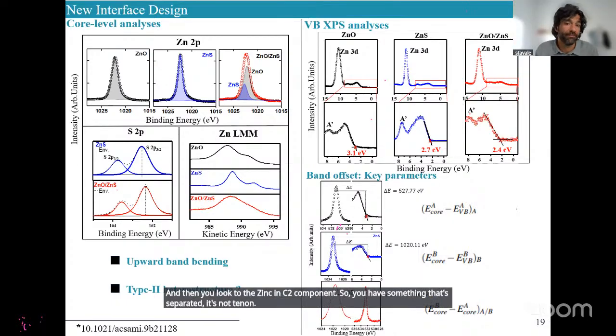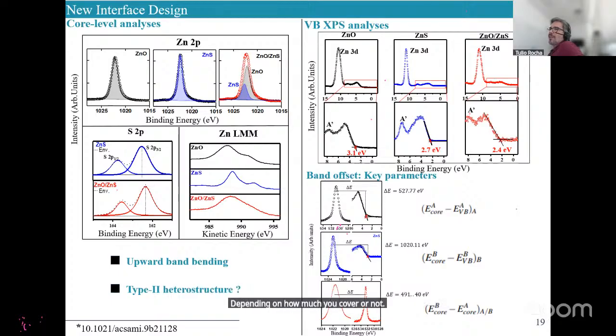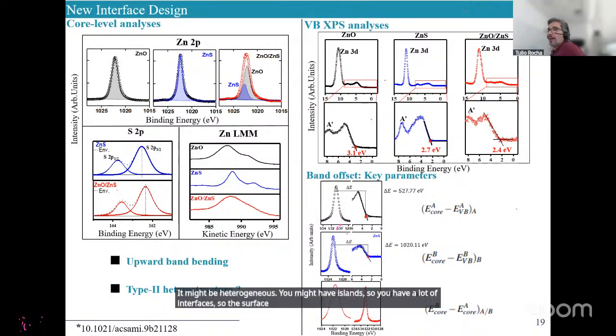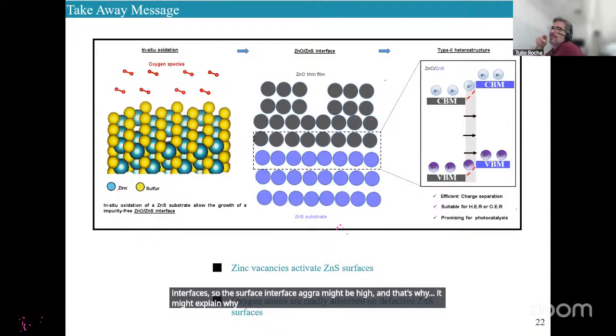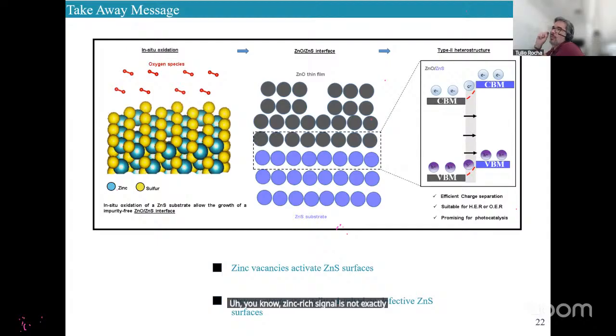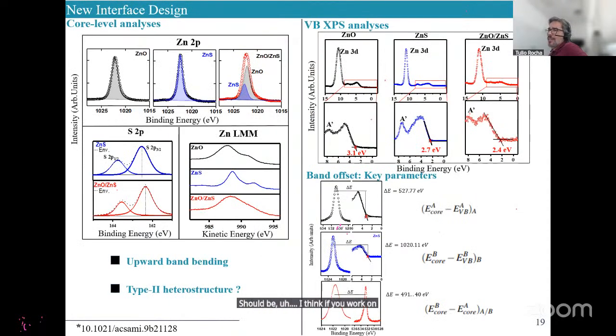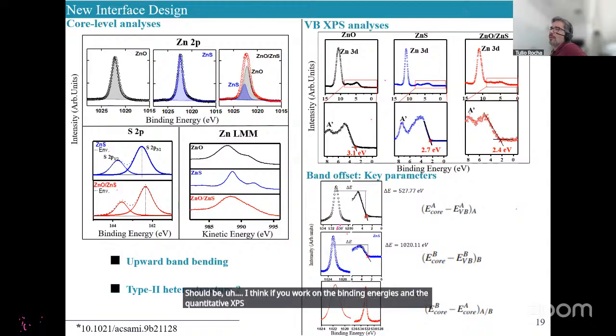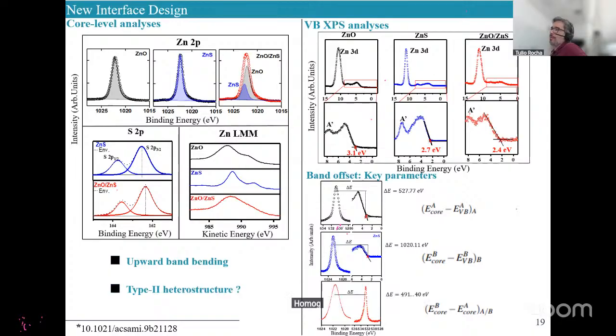It's not ternary. And at the end of the day, this means that all the spectra you see should be a linear combination of these things, depending on how much you cover or not. It might be strongly heterogeneous. You might have islands, so you have a lot of interfaces. So the surface interface area might be high, and that might explain why your zinc-rich signal is not exactly like the ZnO single crystal, because you have a lot of defects, it's a defective structure. It's not the ZnO single crystal after sputtering and annealing. Yes, so then you have broadening, and then you might lose some features. I think if you work on the binding energies and the quantitative XPS, you can rule out the idea that you have a homogeneous mixture or a ternary compound or whatever.